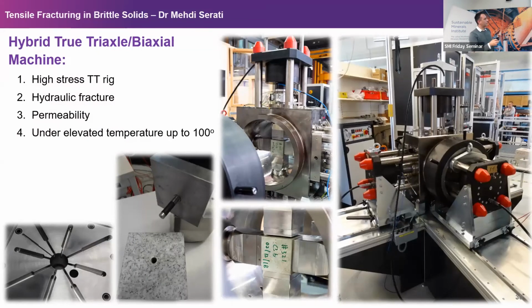For that project and for that spalling strength, we have access to this. Some of you may know this facility available at UQ Civil. So it's a true triaxial testing system, but it's a 4-in-1 kind of machine, because not only can you measure a true triaxial up to high stresses, up to under 85 tons, near 90 tons, on different sample sizes from 50 mil to 200. If you do the math on the 50 mil, you can go all the way to around 350 MPa to 320, which is enough to study most of hard rock.